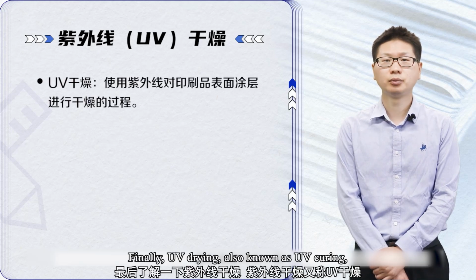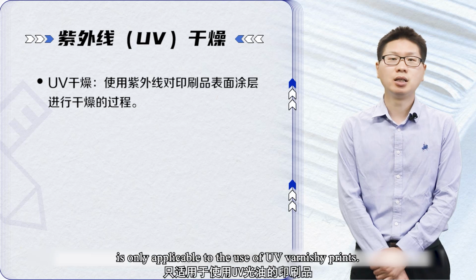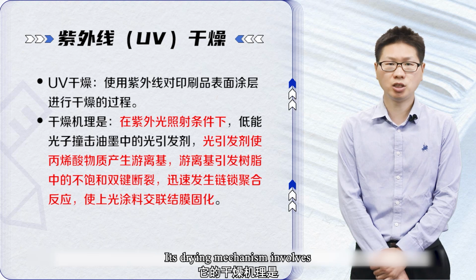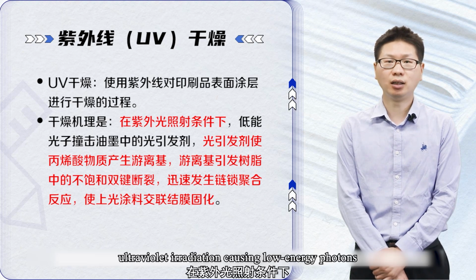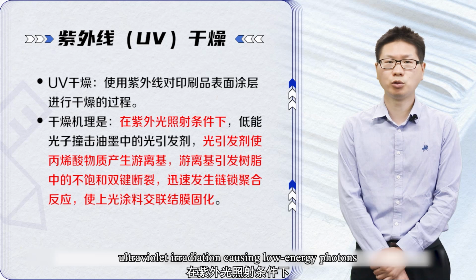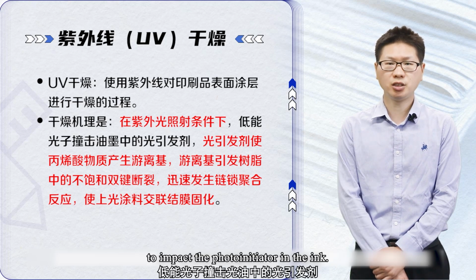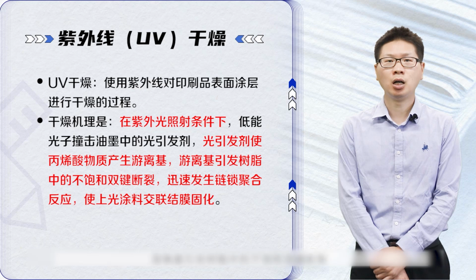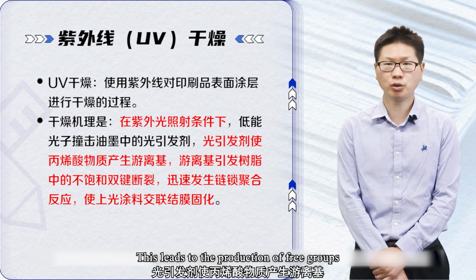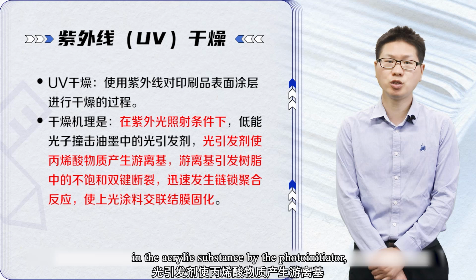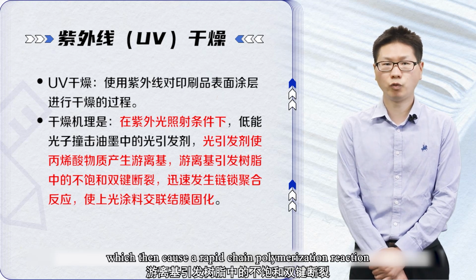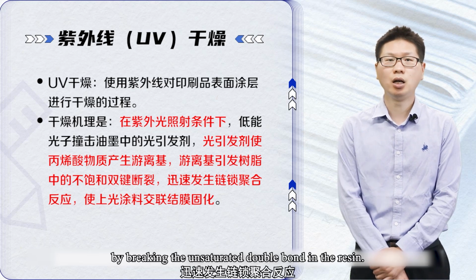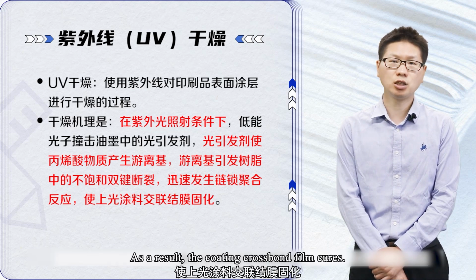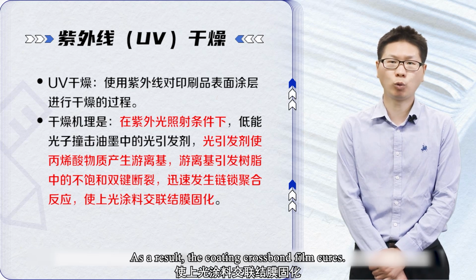Finally, UV drying, also known as UV curing, is only applicable to prints using UV varnish. Its drying mechanism involves ultraviolet irradiation causing low-energy photons to impact the photoinitiator in the ink. This leads to the production of free radicals in the acrylic substance by the photoinitiator, which then cause a rapid chain polymerization reaction by breaking the unsaturated double bond in the resin. As a result, the coating's cross-linked film cures.